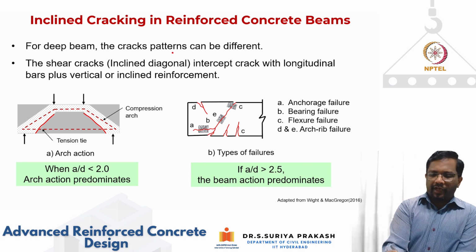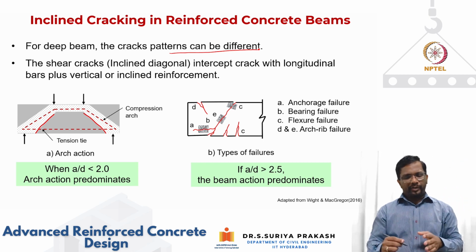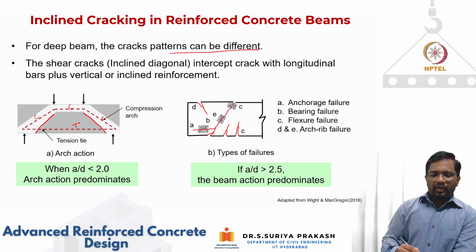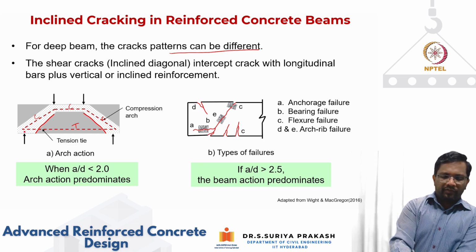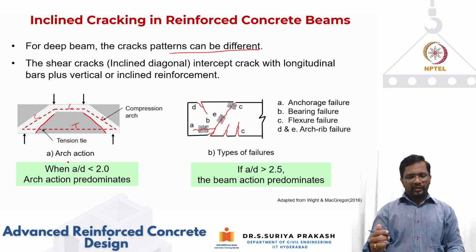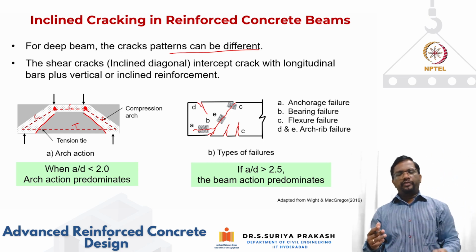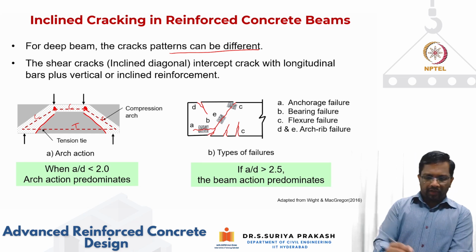Okay, so for a deep beam, the crack patterns can be different. You can see here, when you test a beam at an a/d ratio of less than 2, we have seen that arch action starts dominating the behavior, and you form this kind of arch. You have a compression strut, and then you have a tension tie. Depending upon how you anchor, if the tension tie is not anchored, it can fail in an anchorage mode, or the nodes where the compression struts join can locally crush. So you have different types of failure modes that are possible.